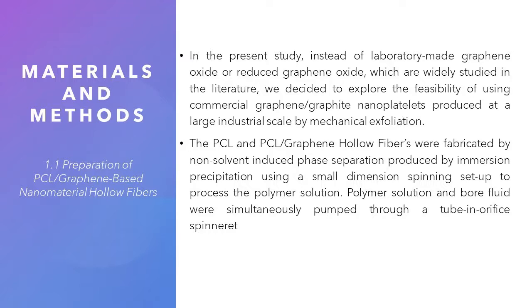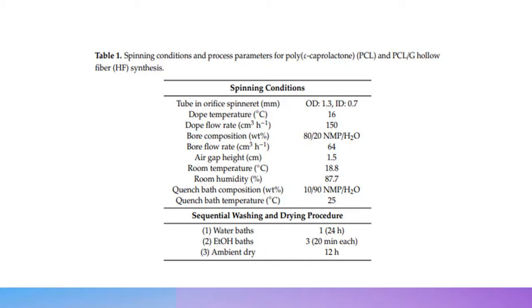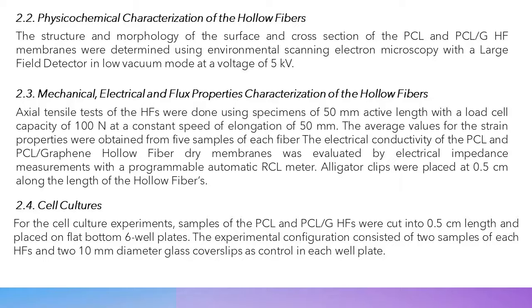Polymer solution and bore fluid were simultaneously pumped through a tube-in-orifice spinneret. Here, as you can see, the formation conditions for the fibers are summarized in Table 1. From each polymer solution, several meters of hollow fiber membranes were prepared, and only homogeneous and reproducible sections were selected for experimental purposes. Physicochemical characterization of the hollow fibers. The structure and morphology of the surface and cross-section of PCL and PCL graphene hollow fiber membranes were determined using environmental scanning electron microscopy with a large field detector in low vacuum mode at a voltage of 5 kV.